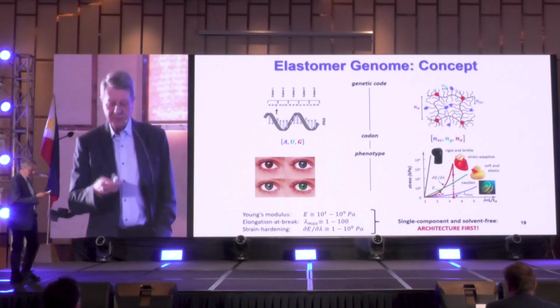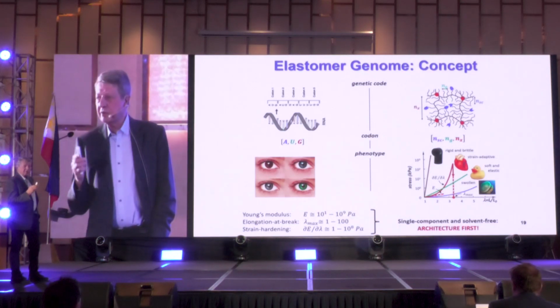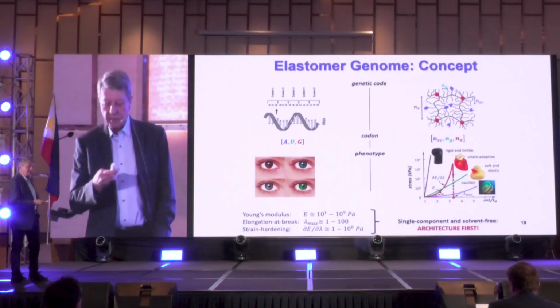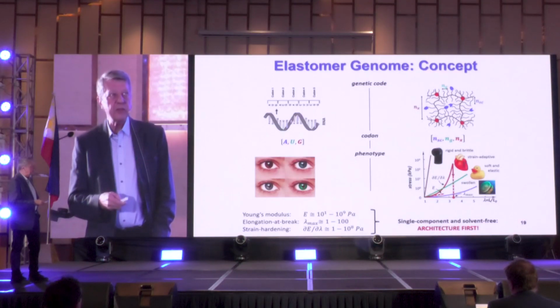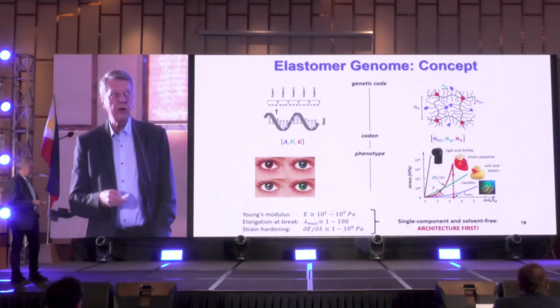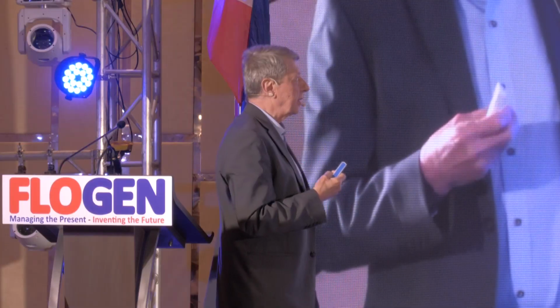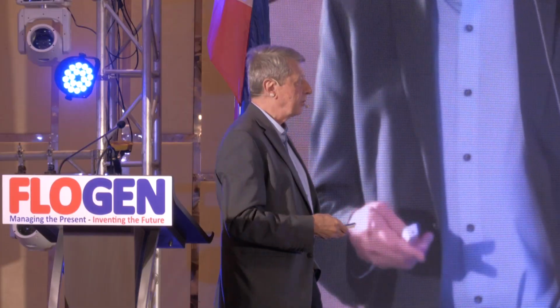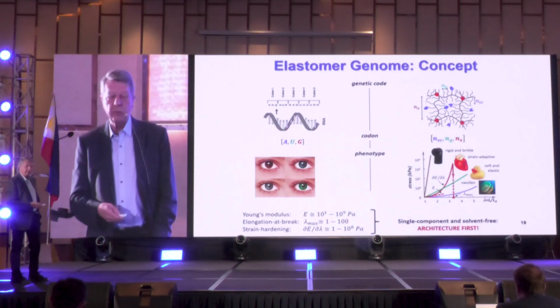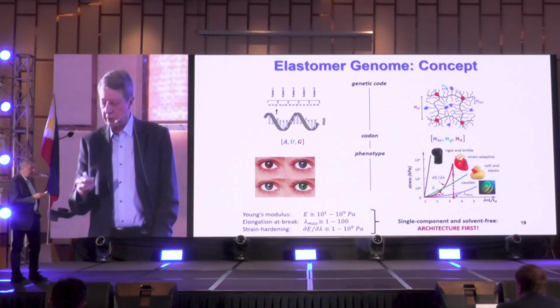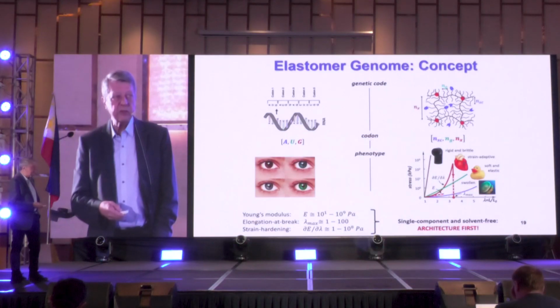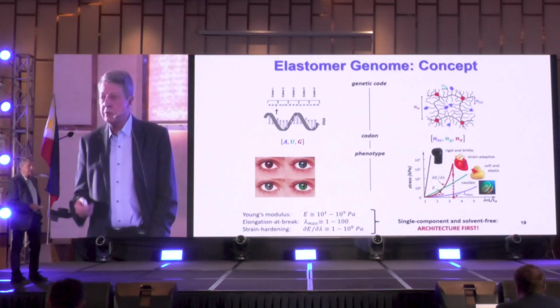Next one. Okay. So, in fact, these materials are very soft, but also you need to cross-link them. So we have 3 parameters. This would be the length of a side chain, this would be grafting density, and then cross-linking density. So these 3 parameters are nearly like a genetic code for this material, and you would like to make them very similar to tissue. Tissue has very different properties than typical polymers because they can be either rigid but also brittle. Anything which would include even carbon fibers would behave in such a way. Or you may have very rubbery material, extremely soft. I showed you even this super soft material. But we can also have tissue which has so-called strain hardening. So can we reproduce such behavior in polymers?